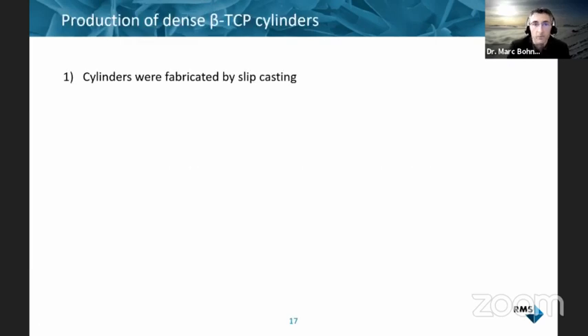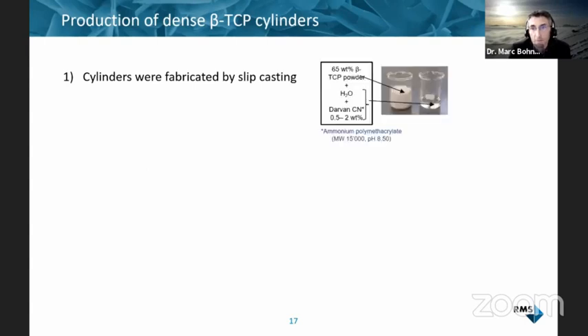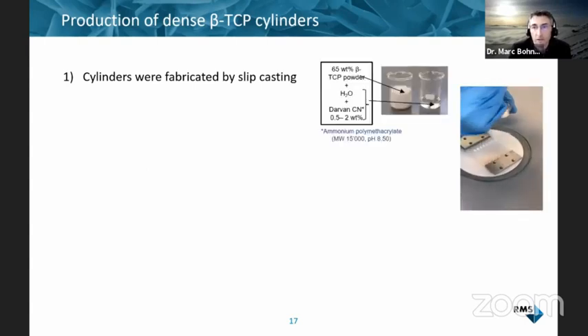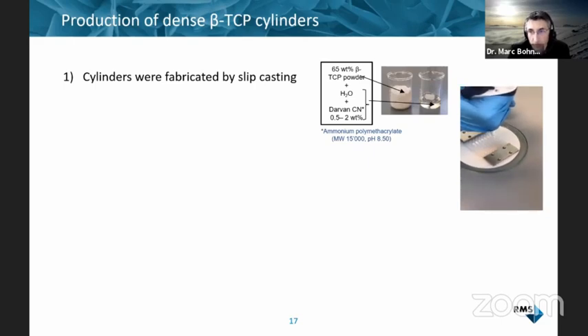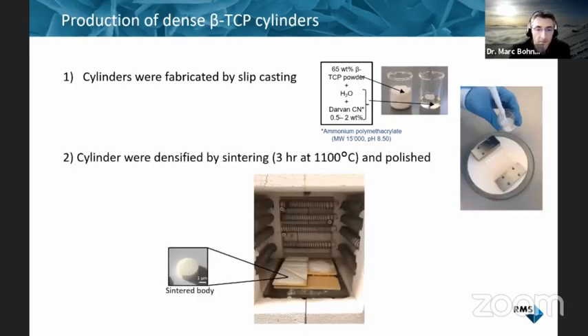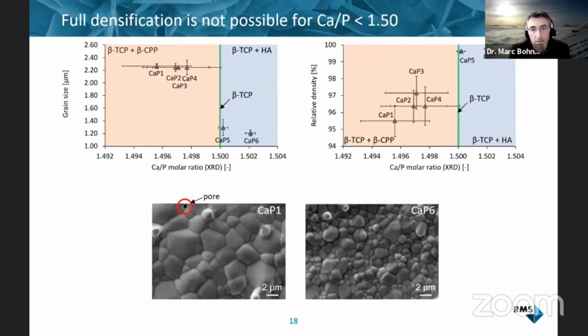Then the next step was to produce a dense beta-TCP sample. I had the help from Jean-Christophe Ornay from Université Valenciennes for that. He showed us how to produce the dense sample by slip casting. We sintered the samples, and then we characterized them in terms of grain size and relative density. Here I'm showing 6 samples that we used further on in the osteoclast study.